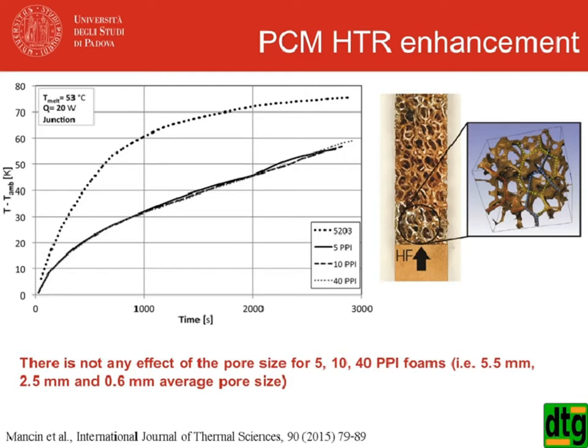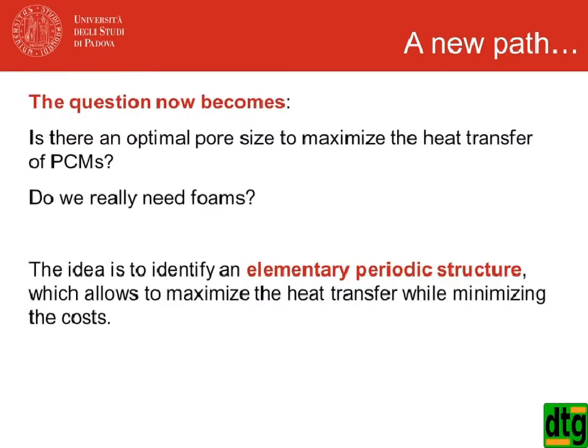And then we have another important result from this. It is basically the fact that the different foams with 5, 10, 40 pores per inch perform exactly the same. So there is not any effect of the pore size. A 5.5 millimeter or 2.5 millimeter or 0.6 millimeter average pore size do not have any impact on the performance of the system. So this suggests something, the research path.